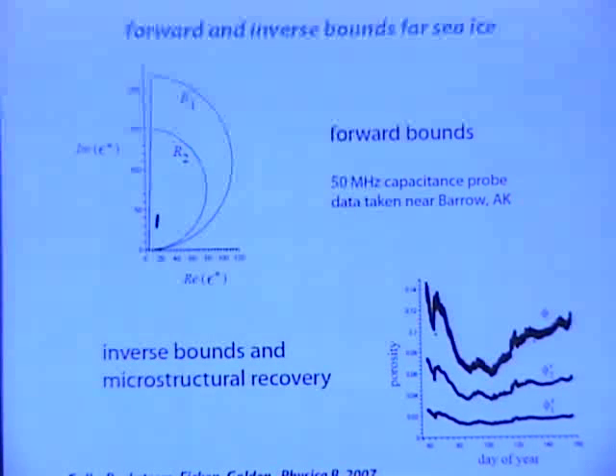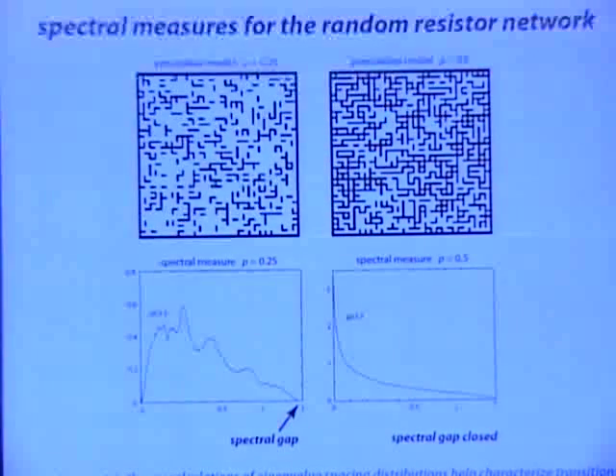These are just some examples of these bounds in the complex plane. This is some of the inverse problem associated with this, where we can derive rigorous bounds on the brine volume fraction. Now, for this so-called random resistor network, or the percolation model, you can compute what is called a spectral measure for this, where the gap in the spectrum, it naturally lives on 0, 1.